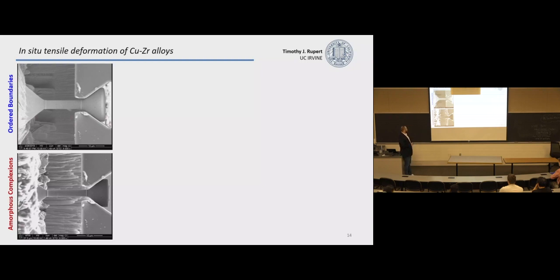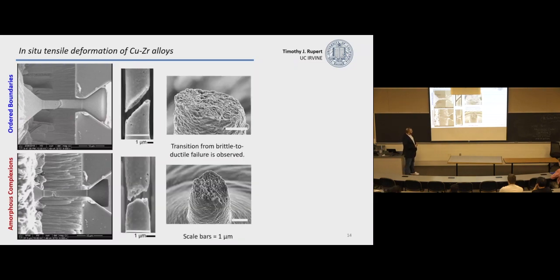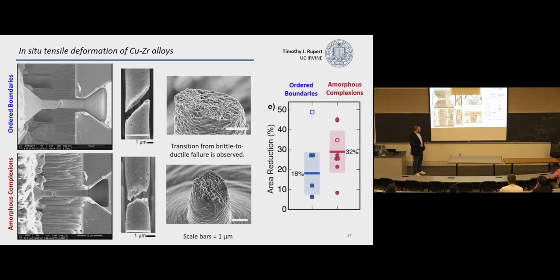When you start to pull on this, you fail rather abruptly here, whereas you stretch and pull out for the sample with amorphous complexions. You can pull out these images and see much more clearly. There's almost no global plastic or local plastic strain here. You get lots of plasticity here when you have amorphous complexions. And then we can measure the ductility in terms of area reduction and see that we've had an increase of about 2x by adding those amorphous complexions.